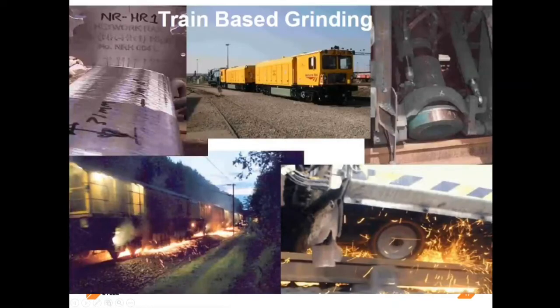So how do you manage that? Well, the solution to both loss of profile from wear and cracks is train-based grinding. Milling as well. Milling is becoming more popular, but grinding is the dominant way of managing rail defects. So you take one of these trains, they've got a series of grinding stones on the underside, and you'll give them a pass of the track, removing maybe 0.2, 0.3 millimeters of the steel. And if the cracks are 1 millimeter deep, you might need several passes in order to clear the cracks and reprofile the rail. And that's how you manage the railway to get maximum life out of your asset. If you allow the cracks to grow and become unpredictable, you have rapid failure and premature failure. Whereas you maybe have 12, 13 millimeters of material lost through grinding before you have to change the rail, and that could be decades. I mean, a rail in tangent track can last 50, 60 years in the network if maintained properly.